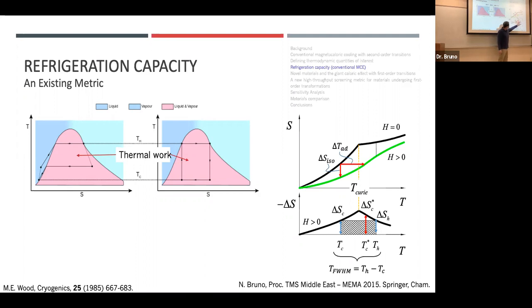So if we want to have a thermodynamic cycle that exhibits reversible thermal work, we can quantify this, the size of this rectangle underneath our delta S curve. And we can use that rectangle, if we use the same parameters for all our different materials, to compare them. To say, oh, this material might give us more thermal work than this one under some constant magnetic field or some ramped, say like 1 or 2 Tesla, applied magnetic field.